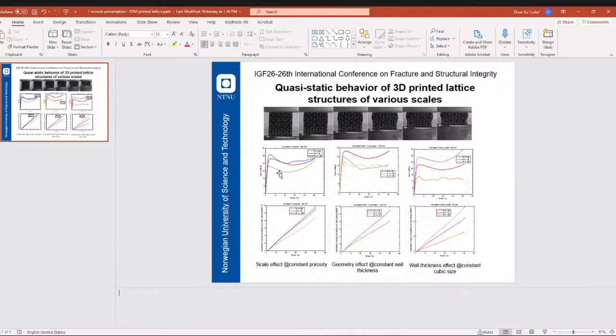We suspect that these lattices have similar compressive behavior. As you can see from the curve, all of them had only one peak, which is the ultimate compressive strength, and only one valley here. So that means the failing mechanism for all the lattices is global instead of buckling layer by layer.